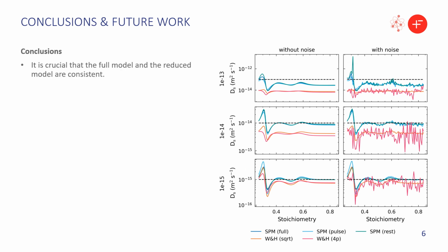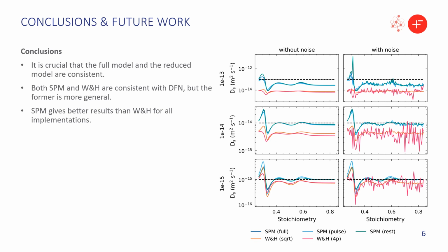So to conclude, what we've seen is that it's very important that the full model we use in our simulations and the reduced model we use in our fits are consistent. And in order to achieve that, what we did is take the DFN half-cell model, use asymptotic techniques to reduce it, and we found both an SPM-type model and a Weppner and Huggins model, but for the latter, we need to take extra assumptions. So actually, we suggest using the SPM model because it's more general. And that's supported by the comparison with both synthetic data and experimental data, because the SPM tends to give better results than the Weppner and Huggins for any implementation.